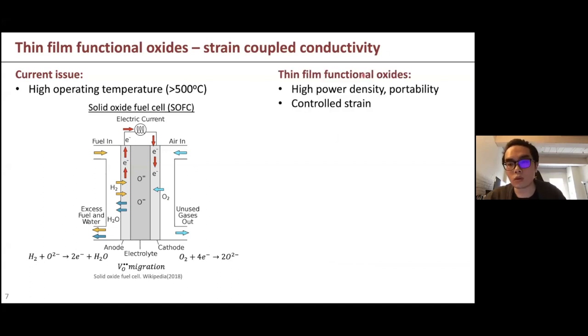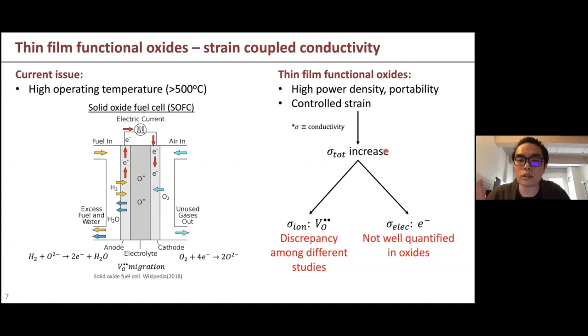Originally, if we were just talking about the bulk material, that wouldn't be possible, because it is unlikely that you can create enough strain to cause a change in the bulk material, especially this kind of brittle material such as oxides. However, nowadays things are getting smaller and smaller, so we can have functional oxide thin films. If it is thin enough, then we can introduce larger strain than we could achieve in bulk material. And in fact, even if you don't want the strain in your device, you will still get some residual strain after you grow the film, because the film is very thin and very easily affected by all external forces. So here, we already know that conductivity will increase when we apply the strain.